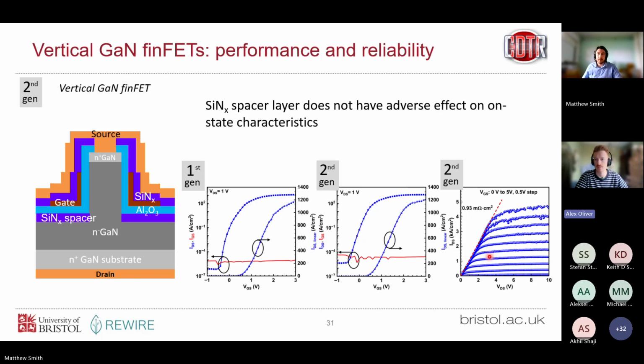Great. So Pallavi has asked, what was the mobility for the vertical GaN FinFET, as etching the fin will degrade the mobility? Yeah, similar to John's question earlier, I think. If we just look at the IDVG characteristics, transfer characteristics on screen here, it looks like we've not seen too much of a degradation when we include this spacer layer, which we know has an effect on the fin sidewall trapping effects, the drift in the threshold voltage. So measuring the mobility directly is very challenging in these vertical devices. We can't make a nice Hall measurement structure that's going to tell us mobility in the lateral direction, not the vertical direction. But what we can say is these modifications that we're making to improve performance don't really seem to affect mobility that much.